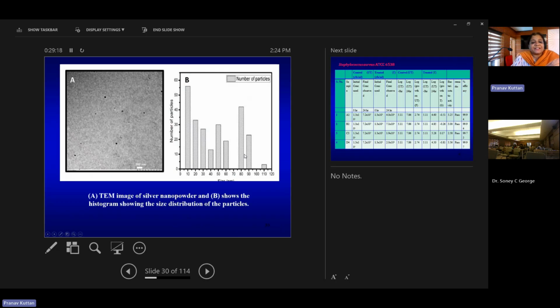So this is the characterization of the silver nanoparticle. As we can see, small particles of silver can be seen on the left side, and the right side is the histogram showing the size distribution of the particles. We can see that almost all the particles are of size lesser than 100 nanometer.